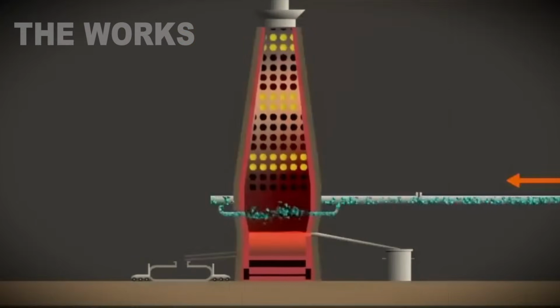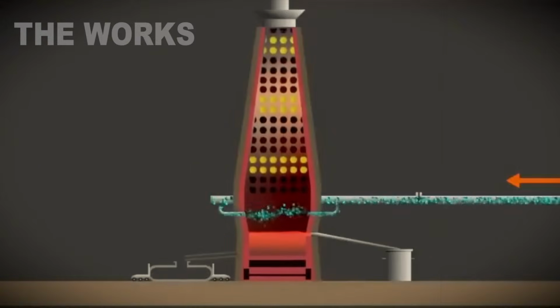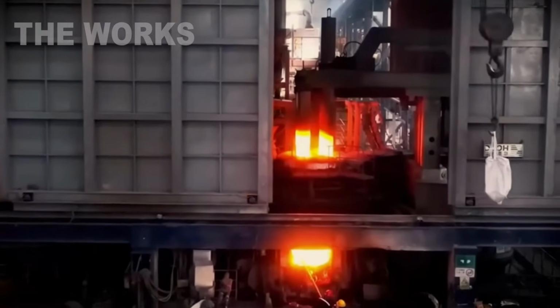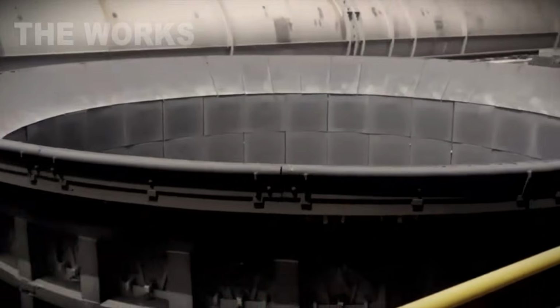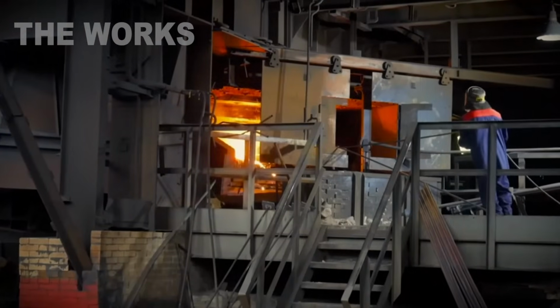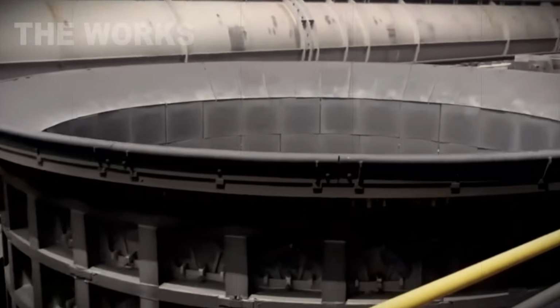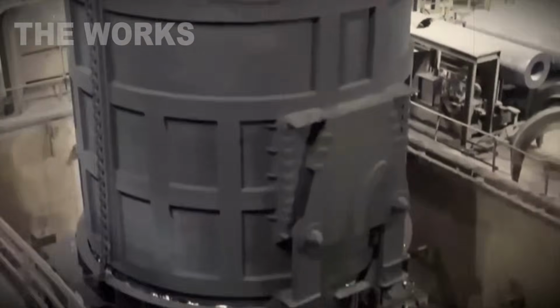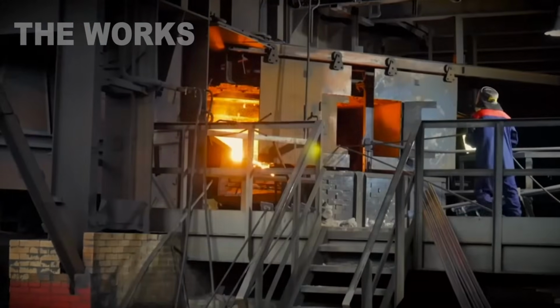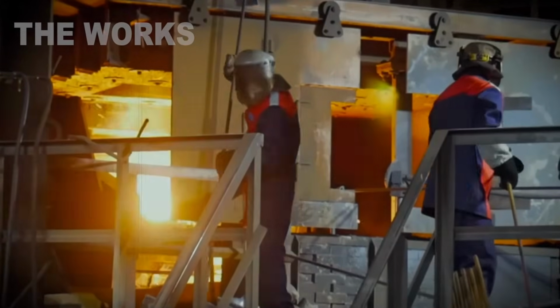Hot air blasts in from below. Temperature, 2,200 degrees. Pressure, 60 pounds per square inch. Flow rate, 100,000 cubic feet per minute. The coke burns, carbon monoxide releases. It strips the iron from the pellets. Temperature in the hearth, 3,600 degrees. The iron melts, flows downward, pools in the hearth.